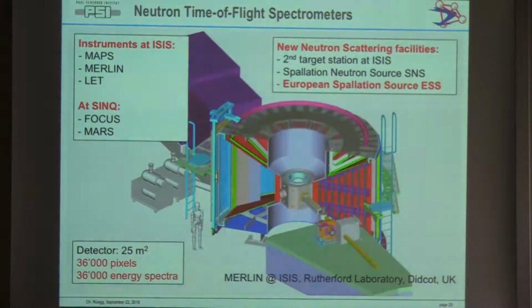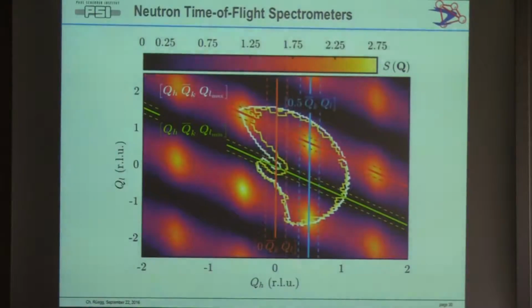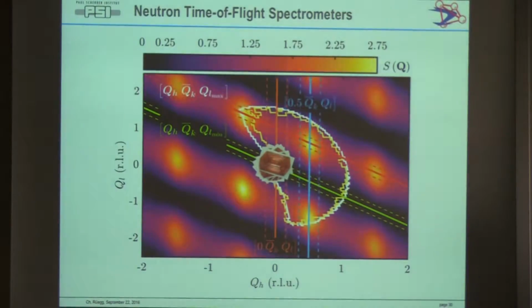They are big machines, unfortunately. They have big helium detectors, 36,000 pixels. Each of the pixels measures an energy spectrum at the same time. So this is at the Rutherford lab, for example, in the UK. You stick in your crystal, and then you can cover this kind of area in Q space. And basically what you do at the same time, you rotate the crystal. And when we do this, let's say for 5 days, we collect the full S of Q and omega information, the full dynamical correlation functions in 4D. So all Q information, all energy information you want.